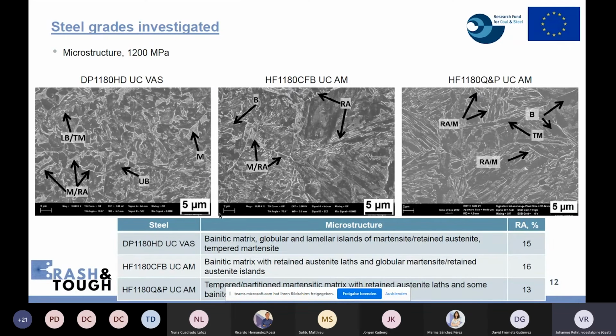And here you can see the SEM images for the grades with 1200 megapascal strength. On the left-hand side, you can see the DP grade with low yield ratio, with lower yield strength. This grade has a bainitic matrix with globular and lamellar islands of martensite and retained austenite, and some tempered martensite is also obvious for this grade. In the middle, you can see the DBF grade with higher yield strength, with higher yield ratio. This grade has a bainitic matrix with retained austenite laths and more globular martensitic retained austenite islands. And on the right-hand side, you can see the QP grade with high yield strength and high yield ratio. This grade consists of a matrix of tempered martensite with retained austenite laths and some bainite.